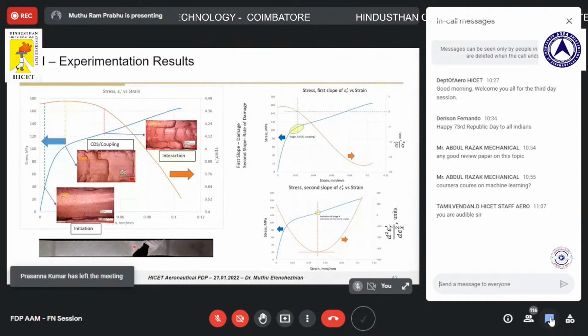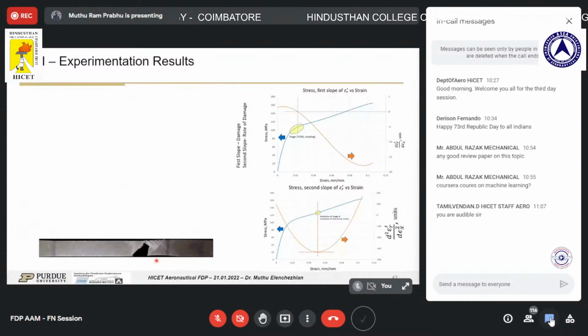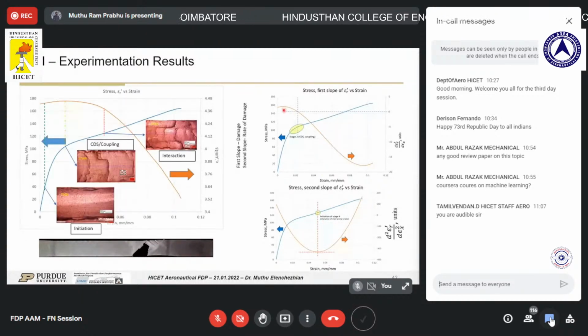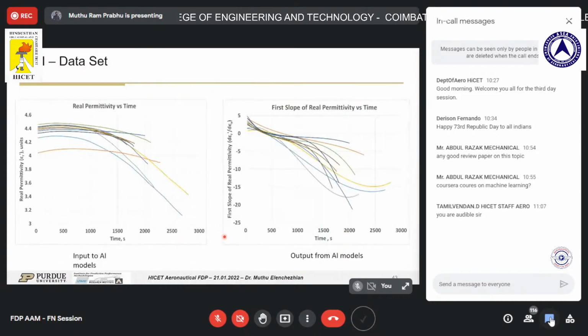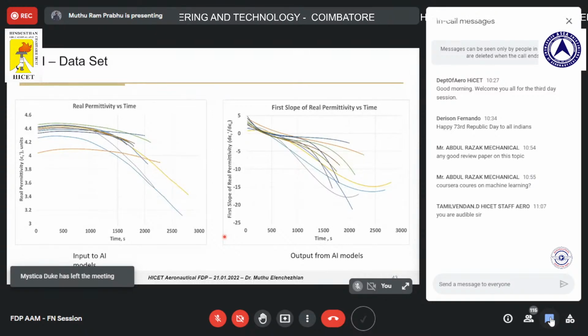Remember, this is for this quasi-isotropic sample over here. For this particular example, we can identify the characteristic damage state point, which is where the actual stage 2 occurs. From the second slope curve, which is the acceleration curve, we can identify where the actual damage accelerates. So this is based on quasi-static testing, and we collected a complete data set. This is for different samples, 11 different samples. The sample set is still small.